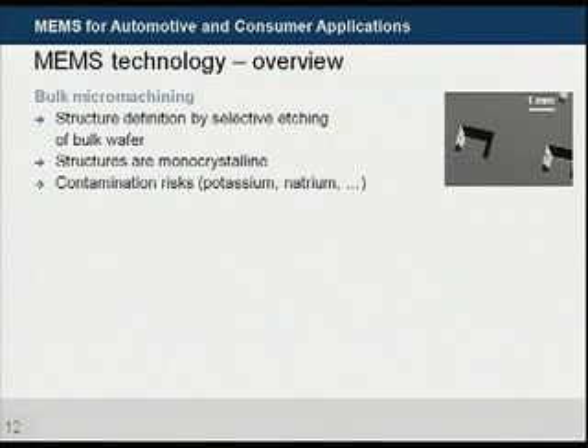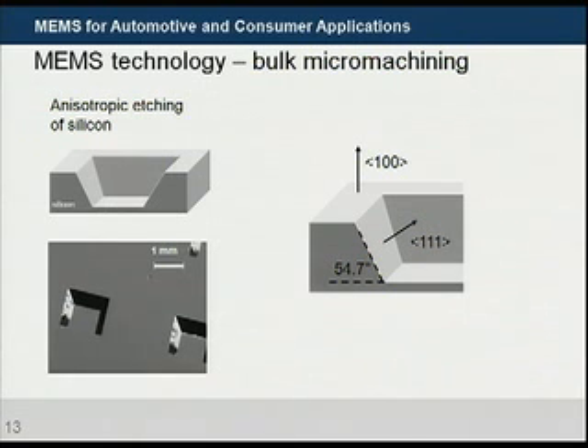Bulk micromachining, as the name says, we are making the structures out of the bulk silicon by selective etching, so the structures are monocrystalline. Here you see the schematics. The silicon as a single crystal has etch rates which are different depending on the crystal orientation, and therefore we can make cavities and membranes using the different etching rates of etchants. For example, the 100 direction is generally etched very rapidly, the 111 at a very low speed, and therefore we can make cavities, holes, and nozzles into the silicon.